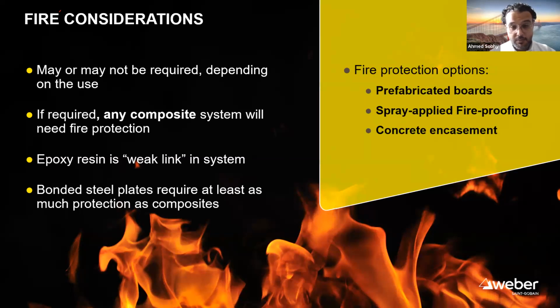Fire consideration is of high importance after the unfortunate incident that happened in London, Grenfell Tower. I don't know if you have heard about it. Fire consideration has been baked into an innate nature that we consider in literally everything that we produce, starting from cement and concrete repairs, and obviously fiber reinforced polymers. The main reason why we consider fire and fiber reinforced polymers is because of the resin, the epoxy. As we said before, it's a petroleum derivative, and it has quite a low glass transition point, so it starts losing its strength at very low temperatures. This is why, when we're talking about a building or structure where fiber reinforced polymers are used and the building falls under fire regulations, it's very important to actually protect the fiber reinforced polymers from fire.